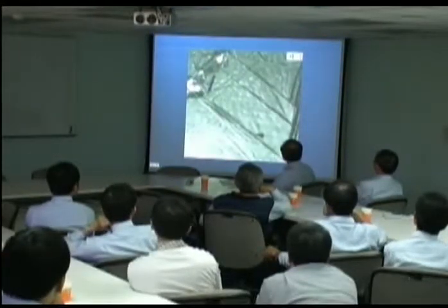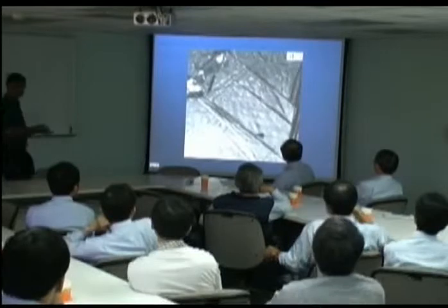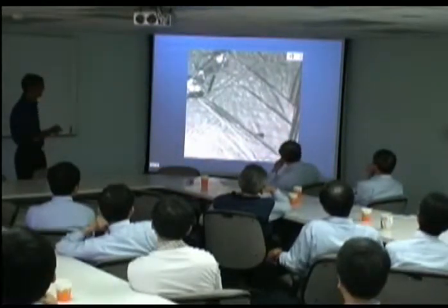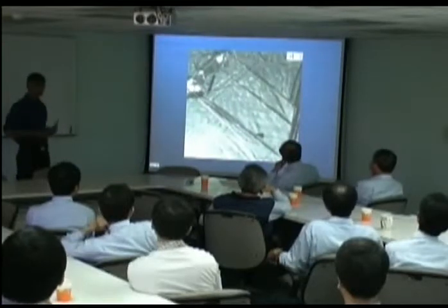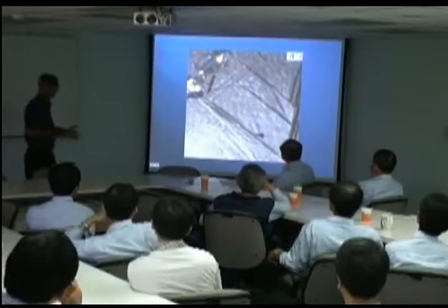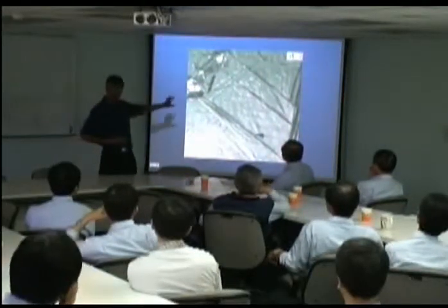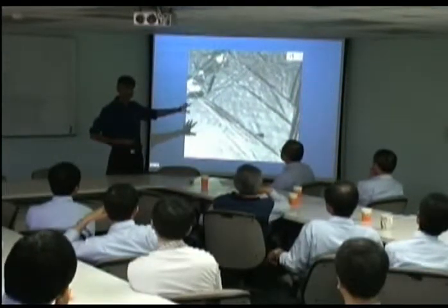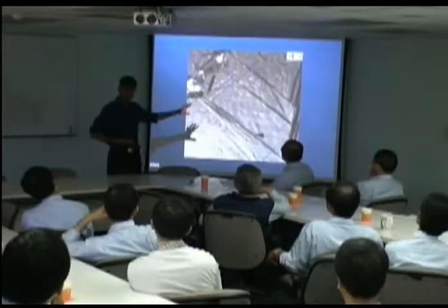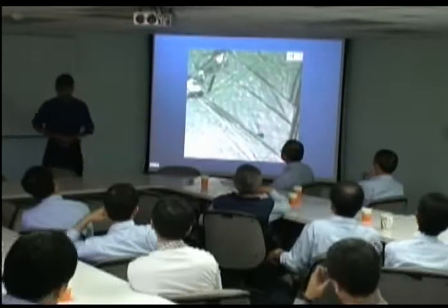Okay. So we can see the mechanism in which plates grow to a certain size. And you saw those plates of bainite growing. We can measure that growth rate directly, compare it with theory, and it is four orders of magnitude faster than would be allowed by carbon diffusion. So completely consistent with diffusionless growth.